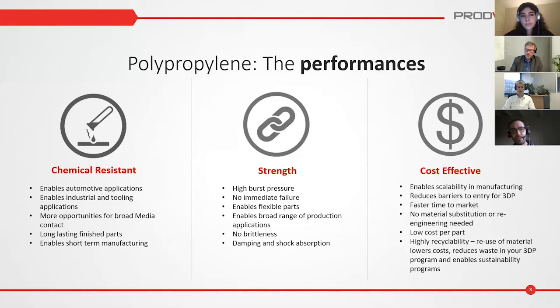Another advantage of using a material that is widely used in traditional manufacturing is that, for instance, if you want to use 3D printing for prototyping, you can then go for injection molding in PP. Then you can use a prototype already in PP from the beginning, which is much more convenient and will allow you to have faster development cycles. Also, PP can be welded to other PP parts, whether they are 3D printed or not, which means that you can 3D print a PP part and have it welded to an injection molded PP part without any problems. So you can combine the technologies for a better result.